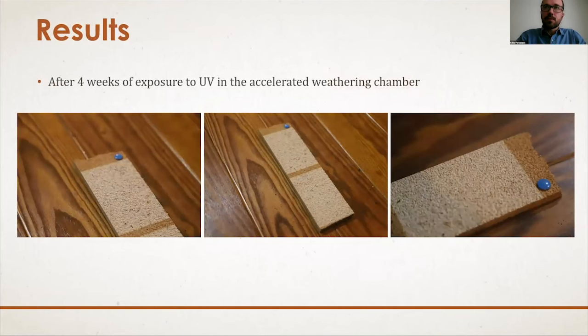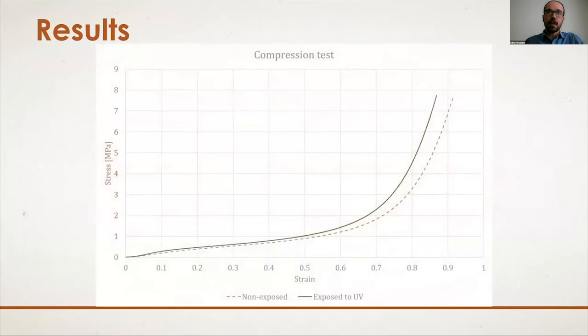So in terms of results, one thing was immediately clear. The aesthetics of this composite were clearly affected by the UV radiation. We can see the discoloration between the exposed region and the non-exposed region. So the degradation of the surface was evident at the macroscopic level thanks to this discoloration. In terms of color, this was more than evident.